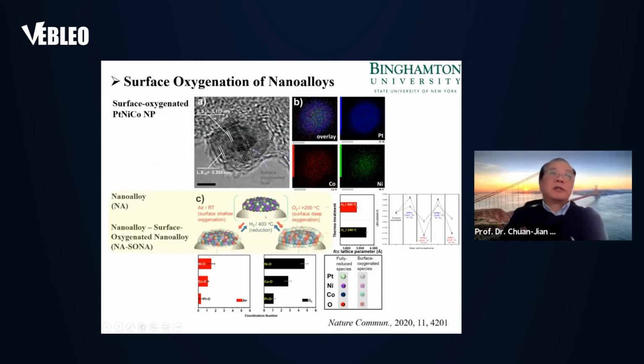In this particular slide, the top panel illustrates a platinum nickel cobalt ternary nanoalloy particle. This particle is oxygenated. The surface layer of 5 layers or so is oxygenated. As illustrated here, you can see the sharp contrast between the core and the shell. It's totally different, right? The lattice is also different. Then you look at the middle, illustrated by the yellow highlighted region. So we can really manipulate the degree of oxygenation.